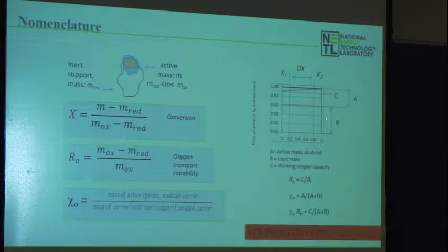And it's interesting to notice the scale of these quantities for a typical carrier. This is the fraction of the material that might be inert, right? If I make a material as an oxygen carrier, you might have 50% of it being a supporting material, and then the remainder of it is the working material, and then of course only some part of that is oxidized and reduced, the amount of oxygen going on and off, because it has the other cation sitting there that you're sticking the oxygen on and off.